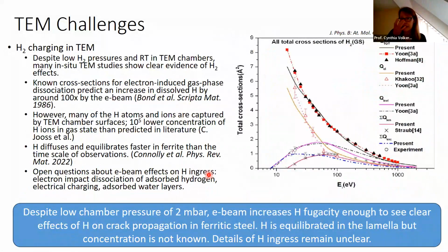Another thing that is always a question, particularly for the case when one tries to introduce hydrogen into these microscopes: there are these so-called environmental microscopes, which is what we have, which allow us to put a low pressure, up to around 10 millibar, of hydrogen into the chamber. And the studies you'll see today are performed at 2 millibar. And all of those who work with hydrogen embrittlement are going to say, well, that's not enough to get anything to happen. Room temperature and 2 millibar of hydrogen is not going to cause anything in ferritic steel.